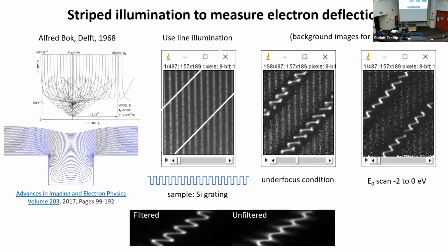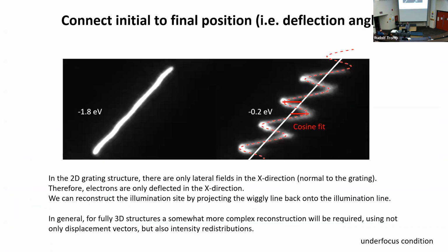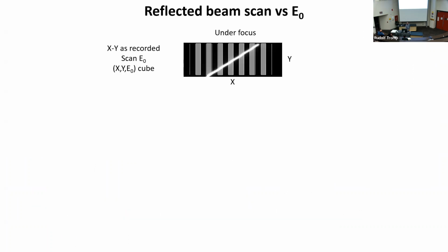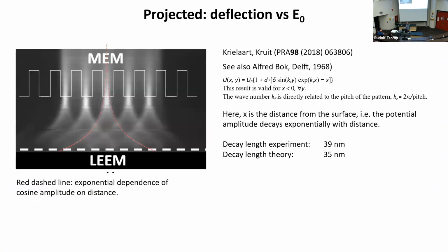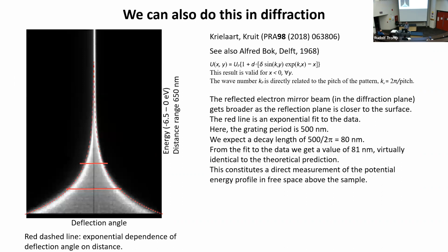Filtered and unfiltered. You see in the unfiltered, it's all smeared out. Here you see this cosine fit. The potential has a cosine shape when you're far away, when you're a few tenths of a volt away. And here is this thing projected as a function of energy and location. You see the fields fall off exponentially, and that corresponds pretty well with the spacing of the grating that we're using.